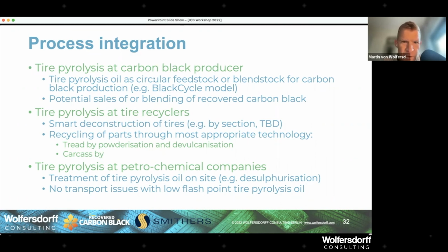Okay. Frederick, if tire pyrolysis oil is used for carbon black production, very little CO2 reduction is therefore expected. You know, the tire pyrolysis oil carbon footprint, I don't have a number in my head, but if you have an Excel spreadsheet or calculator with you, I would calculate 600 kilograms of carbon dioxide per ton of recovered carbon black. And you need to divide it by 40% and multiply it by 50% because that is the mass balance for the oil. And then you get the footprint for the oil, which is less than 1 ton carbon dioxide per ton of oil. So I think it's still pretty good compared to fossil feedstock.